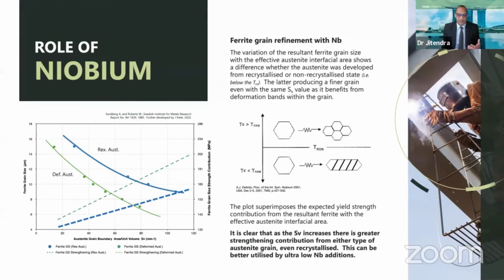And what I want to show you is that we also need to look at niobium in a slightly different way in commodity steels, where it still can play a role. So in this graph, I'd like you to focus on the blue line, which is the recrystallized austenite grain. This is really when we finish at high temperatures and when we have low niobium additions. It typically tells us that as we refine the recrystallized austenite grain, it can still lead to a refinement in the ferrite grain size, which you can see here on the blue line for the right axis. So if we can refine and make a smaller recrystallized austenite grain, even with very small additions of niobium, it should give us contributions in strength. And therefore, that would allow us to decrease the strengthening contribution that could be made from alloying additions of manganese and vanadium.